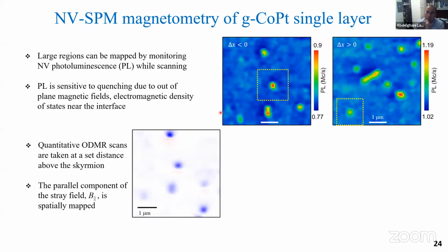But usually, another way we do the measurements, rather than looking at the change in fluorescence, is we do full ODMR. From each pixel, we do this full ODMR and we get the frequency shift. From the frequency shift, we can know the stray field generated by these spin textures. That means if it's off here, there is no stray field, but when you cross these skyrmions or spin textures, you can see positive or negative, red or blue.